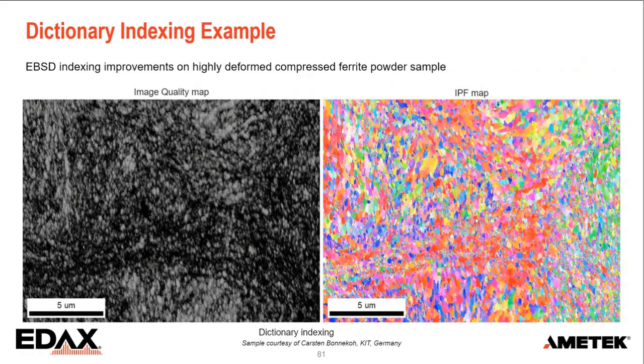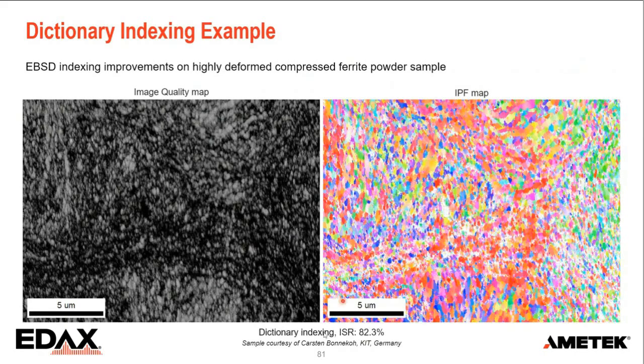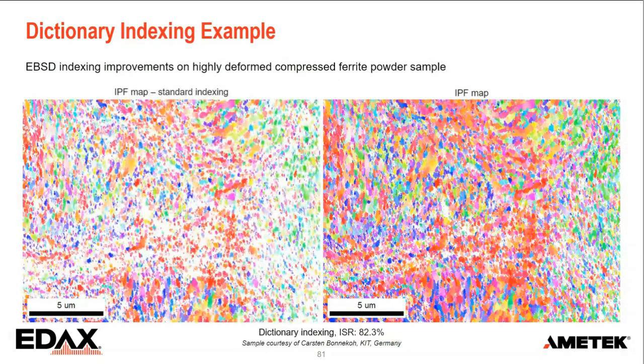When I apply a CI filter, I went up from about 49% to 82%. So that's the original IPF Hough-based indexing, and this is what I can get with the dictionary indexing of those extremely deformed, poor patterns.